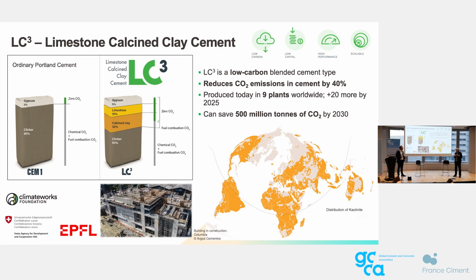So where can we go? We have to find new substitute materials. And this is the logic of LC3. It was known for quite a long time, since Roman times even, that clay becomes a very active pozzolan if you heat it up at a much lower temperature than clinker. What's new in LC3 is that if we put this together with limestone, the two actually react together, and that way we can go to very high levels of substitution, 50% or even more. This is dramatic in the sense that it really can extend this logic of substituted cements.